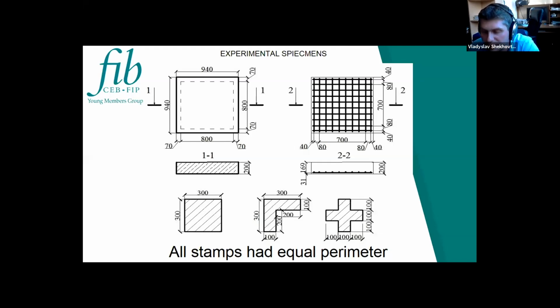So we made the specimens. Here are some parameters. The reinforcement of the specimen was calculated in such a way that we have collapse from the punching, not from bending moment. And if you remember the last slide, the perimeter of the punching pyramid plays a key role in that formula.